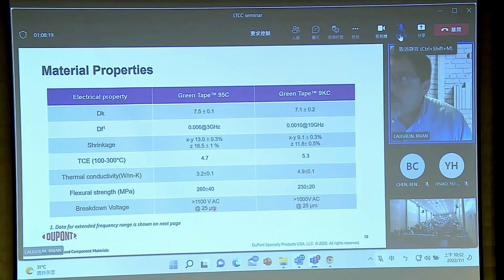And then there's ceramic materials. They're known to brittlely fracture, but that doesn't mean they're weak. So they have high flexural strength when they're fired and fully mature. Yes, they break somewhat catastrophically, which is different than a plastic board, but they're quite strong and they have high fracture toughness. And because they're dielectric materials and fully dense, they have very high breakdown voltage. And so for a power module, they can take quite a bit of current abuse and temperature. And so that makes LTCC a very high reliability technology. And these particular material systems are some of the best out there for all of the holistic needs of a module, not just the electrical design, but the mechanical and thermal design.